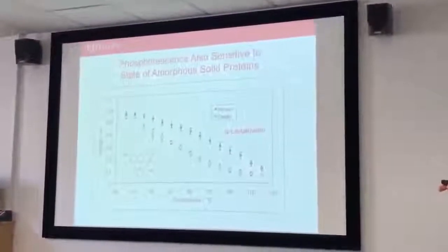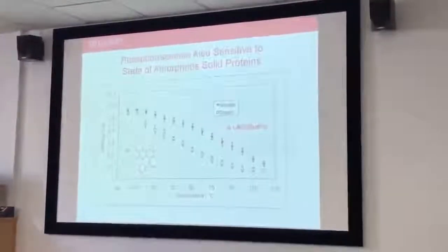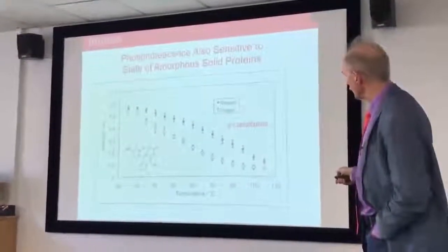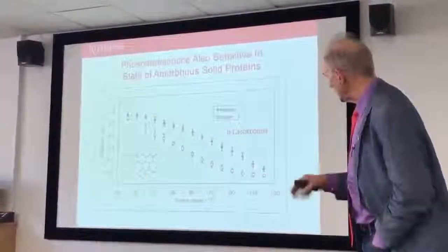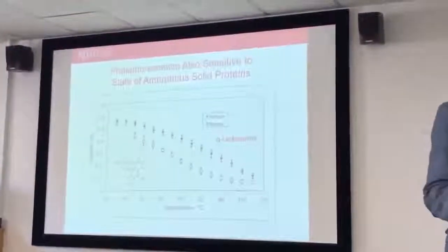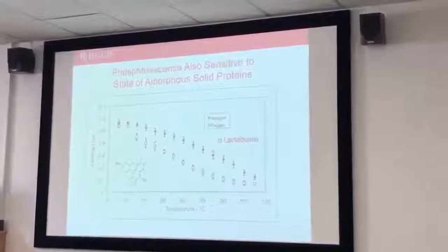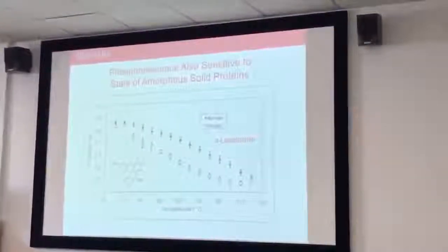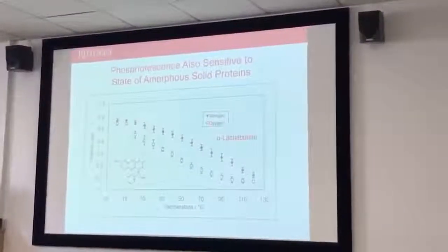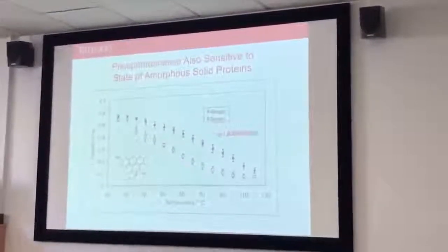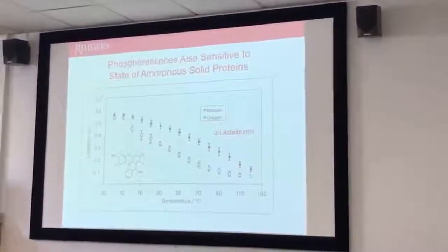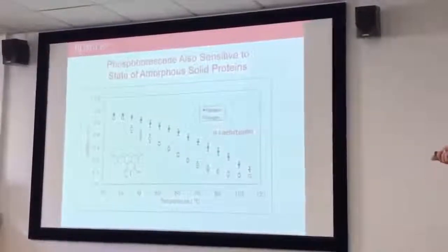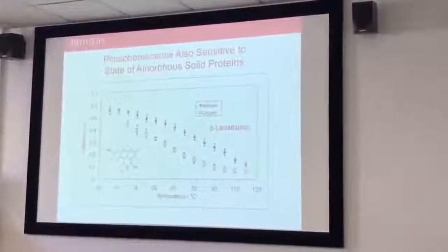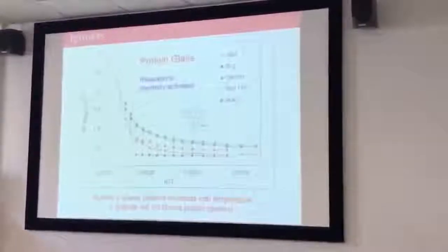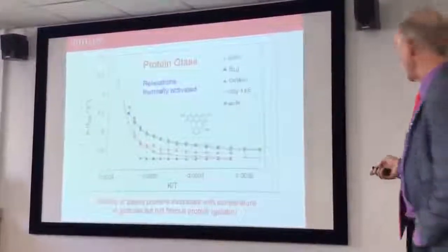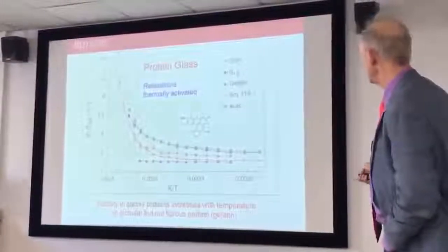So I mentioned the oxygen. There are 1,000 or 10,000, I don't remember exactly, molecules of erythrosin in that film. We spread it out, and it readily forms an amorphous protein glass. We make a measurement in the presence of pure nitrogen, or just air, that's oxygen. And again, you see now the influence of the oxygen. So you can analyze for what the quenching constant is, and you can also analyze for the KNR, and this is how the KNR behaves.